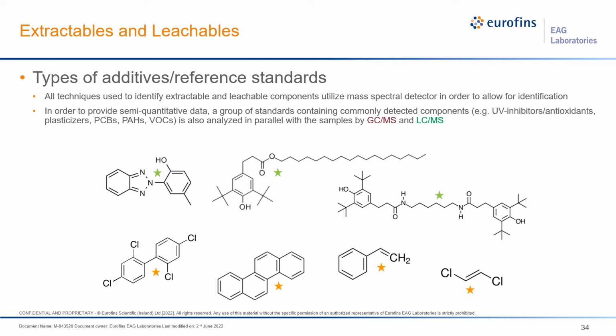So here we see some examples of things that we see commonly. Again, the 3 at the top with green stars, you'll notice that they contain a lot of nitrogens and oxygens. These are going to be susceptible to taking on a charge and are more likely to be detected by LCMS because they're more polar and will be extracted with water or IPA. The 4 components you see on the bottom are more nonpolar, so these are going to be more likely to be isolated from our IPA or hexane, and these are going to be detected by GCMS.